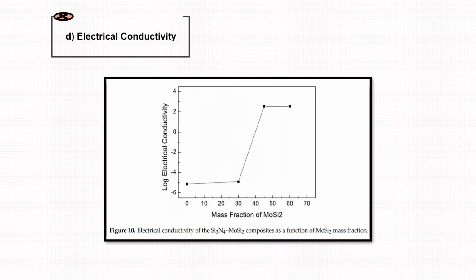When the content of the molybdenum disilicide reached 30 weight percentage, the electrical conductivity was 1.25 times 10 to the negative 5 per ohmmeter. When the content increased to 45 weight percentage, the electrical conductivity increased 7 orders of magnitude and reached 3.45 times 10 squared per ohmmeter. After this value, the electrical conductivity increasing rate becomes flat. This phenomenon can be explained by the percolation theory.